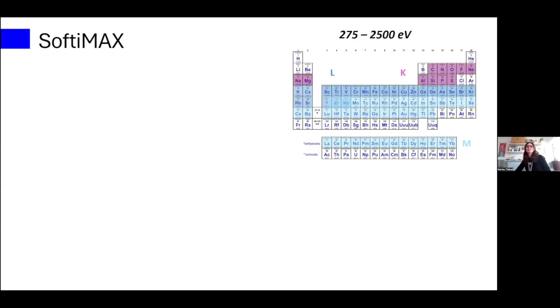Right, then SoftiMAX. What do we do? Well, we are a beamline that covers an energy range from 275 to 2500 eV for the STXM branch, and that covers all of these edges that you can see colored in the system. So as you can see, it's quite a lot. A number of them we cover in the K edge, other ones like iron, for instance, in the L edge, and even other ones in the M edge, the 4f, for instance. So that is what we can do, notably. Chlorine, don't ask me about it because we don't cover it.